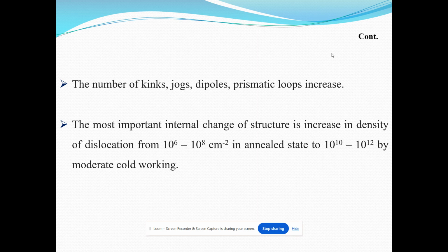The dislocation density increases. In most annealed cases, the dislocation density is in the order of 10 power 6 to 10 power 8 centimeter minus 2, whereas in moderately cold worked material, the dislocation density varies from 10 power 10 to 10 power 12 centimeter minus 2.